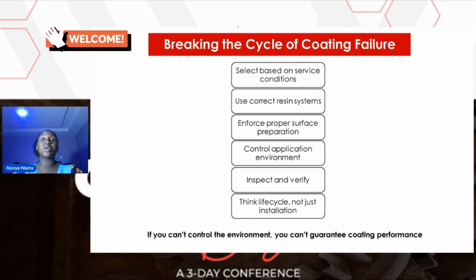Then enforce proper surface preparation. This is quite difficult, but I know it is doable. If the system requires you to clean to Sa 3, there shouldn't be any compromise. That's because the specification writers, those that have put that information together, must have determined that for this system to last the next 10 years, we need a white metal finish, not even near white. And every coating that will be applied on it requires that level of cleanliness to adhere properly.